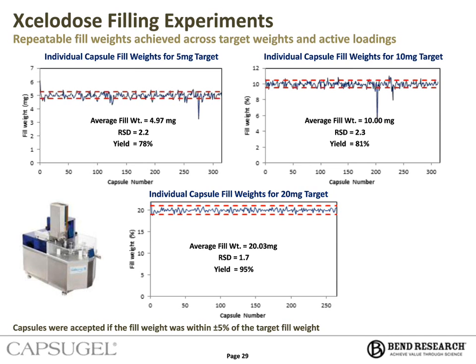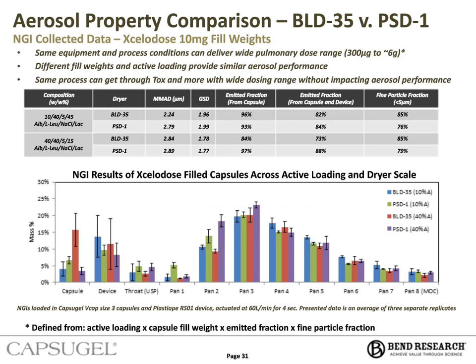But again, and just like what we showed earlier, we had the same NGI impaction results between the 10 mg and the 5, 10, and 20 mg fill weights on the Xcelodose. The deposition profiles, again, were very similar. What we do see, and is kind of expected between a 5, 10, and 20 mg fill, is the emitted fraction out of the capsule and device does decrease with higher fill weights, which is kind of expected due to the different surface area to volume ratios. But of course, this plays into some of the mitigation efforts of specialty capsules that Dominic discussed earlier.